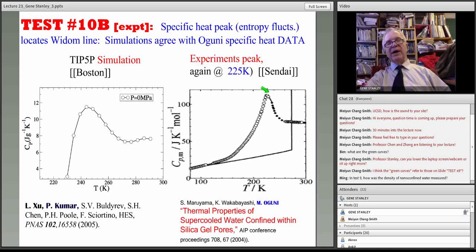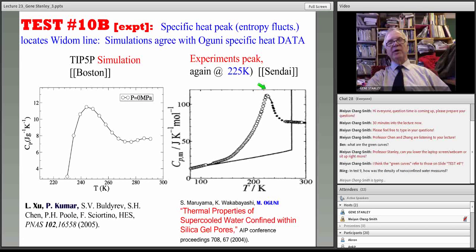But in contrast, with the confined water, we can go as low as we want, and sure enough, there's another maximum at exactly the same magic temperature, 225, the Widom temperature, if you will, and below the Widom temperature, the fluctuations come down again. So what's happening is that above the Widom temperature, we have mostly LDL, mostly HDL, as you saw, and when we reach the Widom temperature, the system is roughly 50-50, that's what we just saw, and therefore the fluctuations are a maximum.